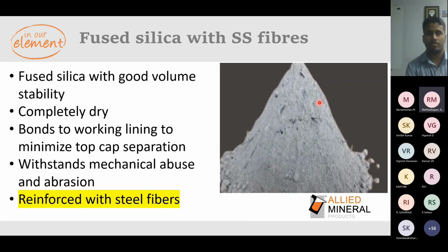So this is one thing where you can see a little bit of needles in this ramming mass. These are needles, these are SS needles. This is again a fused silica, which has good volume stability, completely dry, and bonds very well with the working lining, which is silica. Minimizes the top cap separation. All these dry versions, whatever I'm talking about, minimize the separation between the main working lining and the top cap material. Normally, we recommend this product wherever there's more damage to the top cap area.